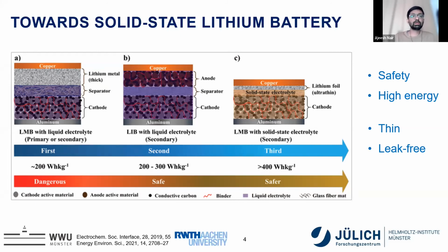But they used thicker lithium metal foil and also a separator, along with the liquid electrolyte. Then what happened is that dendrites were formed, it was very unsafe, and slowly the research community decided that lithium metal is a failure. And then they moved to the lithium-ion batteries of today, which was established by Sony in the 1990s. And that has been very successful since then. Even though a lot of research has been made, the biggest achievements were technological or engineering advancements, whether in which kind of materials are used or what kind of packaging ideas are used.